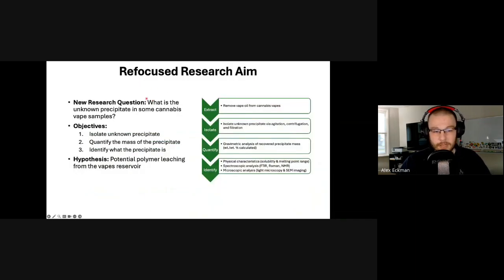And that refocused our research aim to, one, isolate the unknown precipitant. We wanted to quantify how much was actually coming out and then identify what it was. Our early hypothesis was it was potential polymer leaching from the vape reservoir, and really kind of repeating what I had already mentioned. The goal then was just to remove the vape oil. We would isolate it, centrifuge, and filter it. That was really just to clean up any cannabinoids or terpenes that could be retained in the polymer. And then, the unknown. We then wanted to do a gravimetric analysis of that recovered mass to really quantify how much was actually there, and then do a variety of tests to really identify what it was.